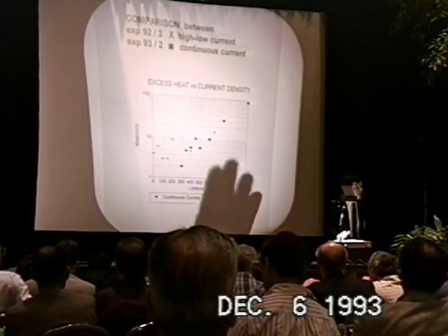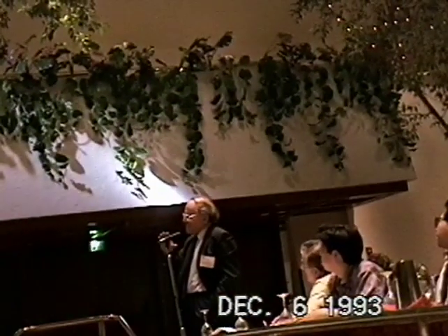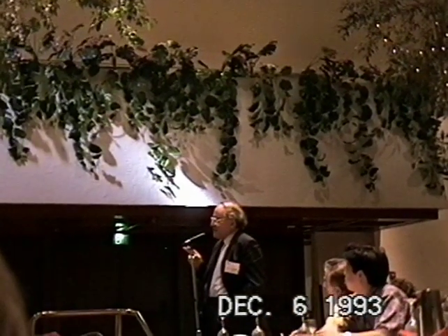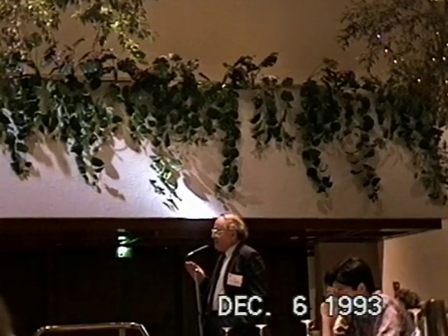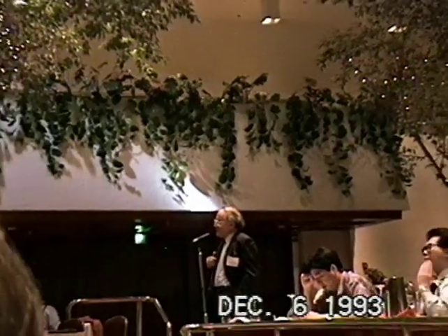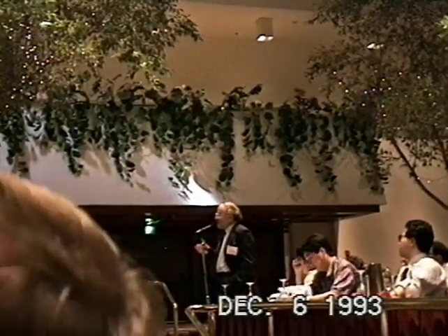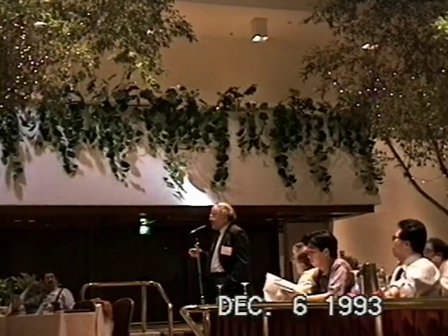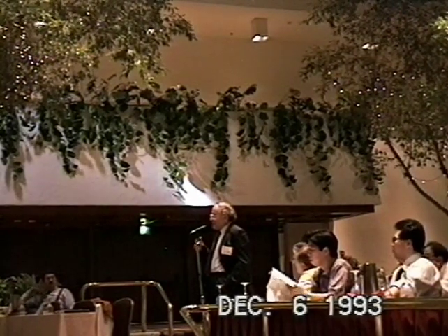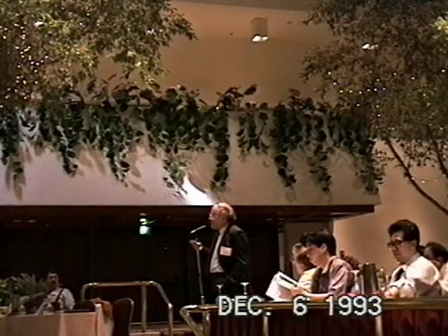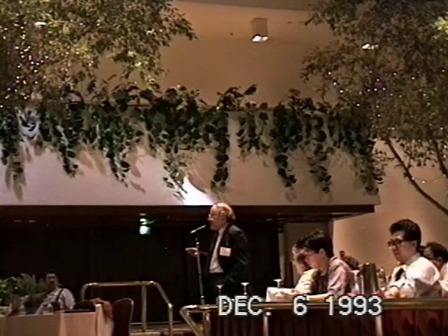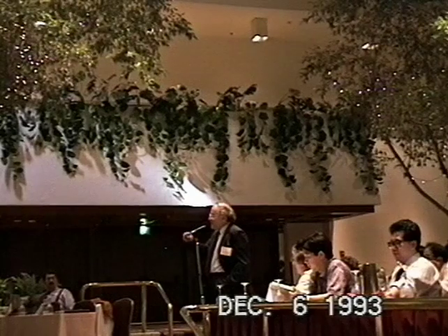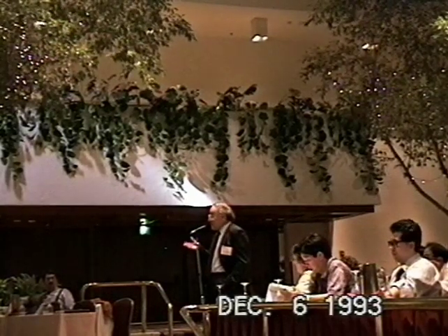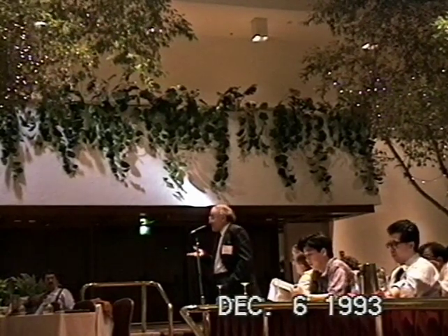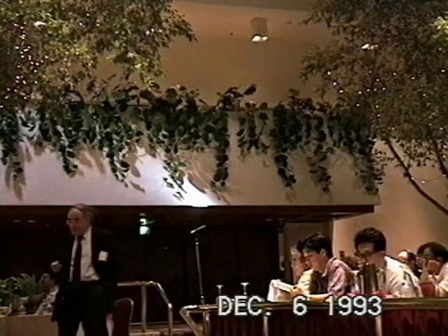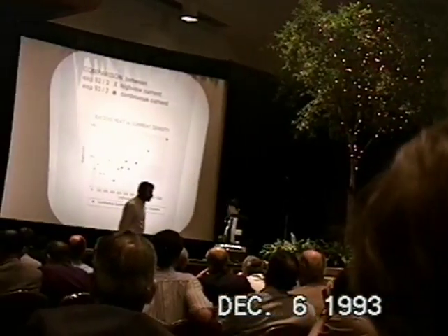Well, may I just make a point here, because it's still the same point. The results you presented last year were done with a particular protocol, namely a high current followed by low current. Those results may be an expression of extension of what we call heat after death. You simply have to drive your system to generate heat, you continue your measurement cycle, and you're getting heat at a lower current density. And in fact, you find that if you have this program to decrease the current density, you can maintain excess heat production at a much higher level than you would if you simply used that low current density continuously. This is a reflection of the effect of the protocol of the experiment on the excess heat generation. That's right. I didn't explain it very well. Thank you very much.